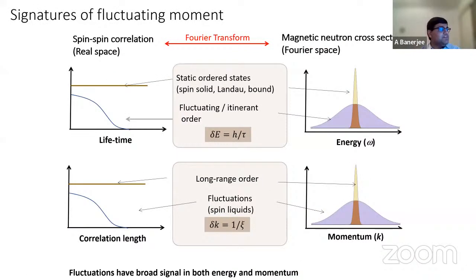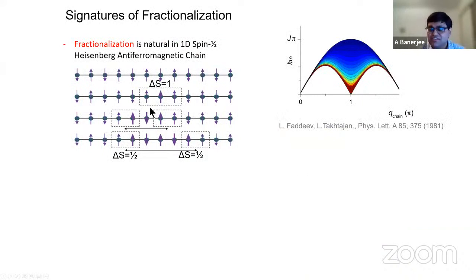But that is not how things look for the spinons. If you have spinons, you get a really fluctuating moment, and you get states which are very broad in energy. The reason is that a fluctuating moment means states with very small lifetime. States with smaller lifetime will be broader in energy, while states with longer lifetime will be sharper in energy. Secondly, states which have long correlation length will have very sharp momentum space features, while states with short correlation length have broad momentum space features. And so when we have fractionalization, what we get is this broad energy momentum signature. And that's exactly how we can get to spinons.